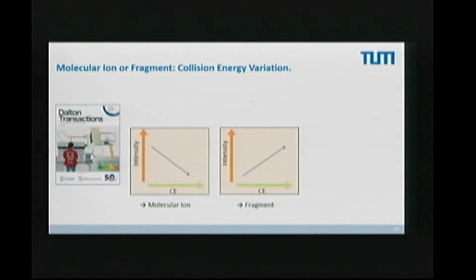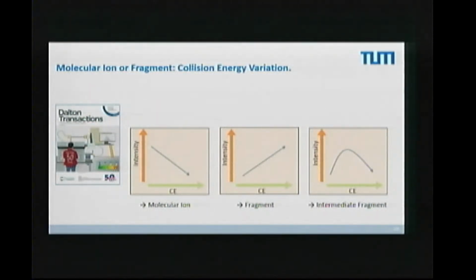Again, molecular ion, intensity of the peak goes down if we raise the collision energy. Fragment, intensity of the peak goes up if we raise the collision energy. So we can discriminate between molecular ion and fragment. And if we have a situation like this, then we have an intermediate fragment which is then fragmented again. By doing this, we can assign all peaks in the spectrum manually, of course.